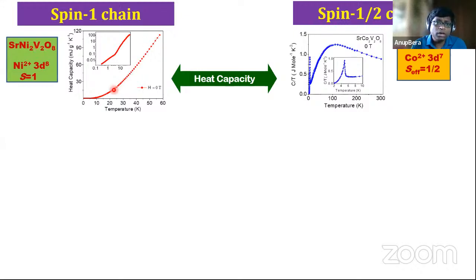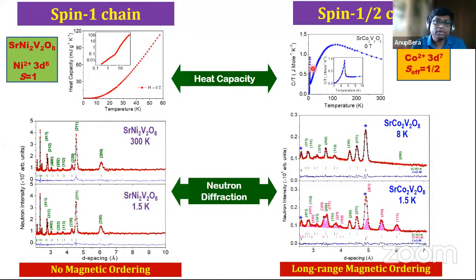Now, if we do the thermodynamic property measurement like specific heat, immediately we see for the nickel compound, if we go down to 0.3 Kelvin, we don't see any characteristic anomaly due to the magnetic phase transition. On the other hand, for the cobalt compound, which has a very similar crystal structure, only the cobalt ion is different, we do see there is a lambda-like anomaly which corresponds to the antiferromagnetic ordering temperature. And the absence of the magnetic ordering for the nickel compound is further confirmed by the neutron diffraction. When we measure neutron diffraction at room temperature and 1.5 Kelvin, we don't see any difference in the pattern. They are identical. There is no contribution from the magnetic lattice.